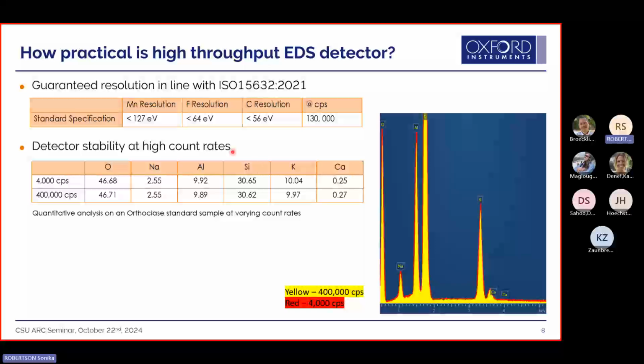But again, the newer detectors are capable of handling higher throughputs. And you can see this was a standard mineral sample, where you can see the quantification at 4,000 versus 400,000. And it varies some, so it depends on what you're trying to do. This is not microprobe. This is not EPMA. Again, the gold standard for us was always WDS, nothing else. But depending on what you're trying to do with the system, it's just something to keep in mind that you can push the limits a lot more than you could historically.